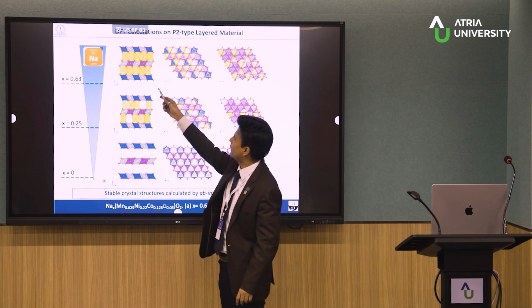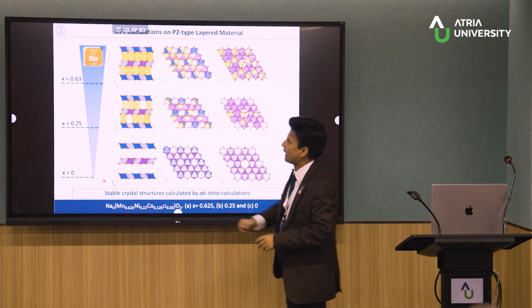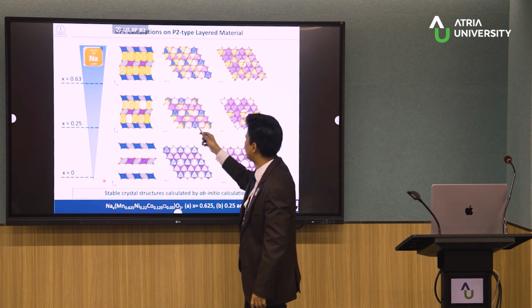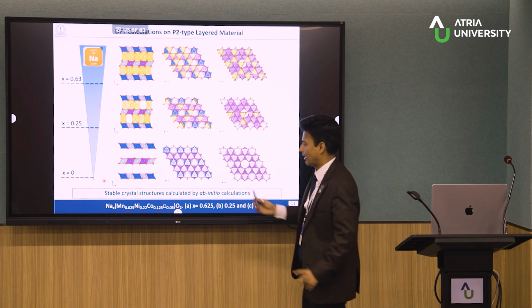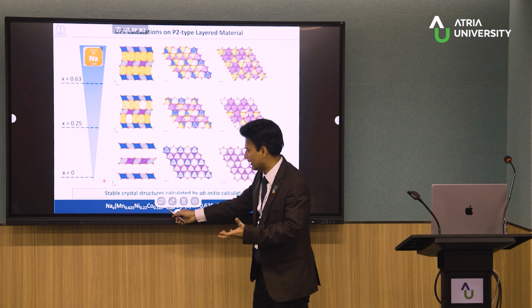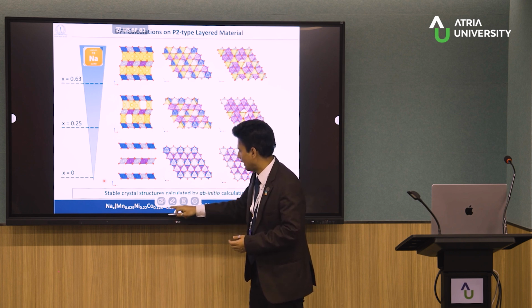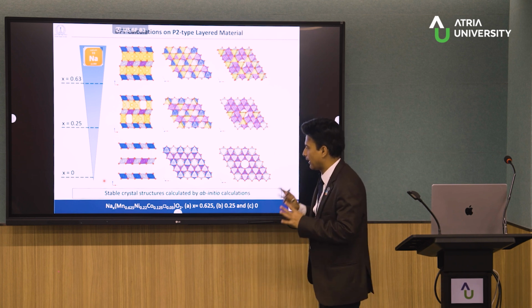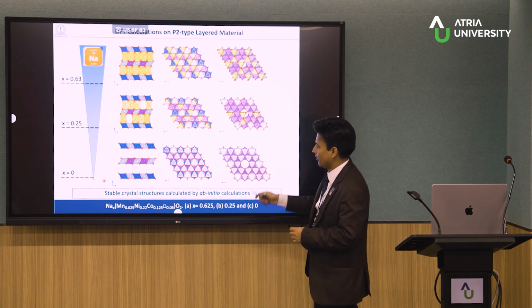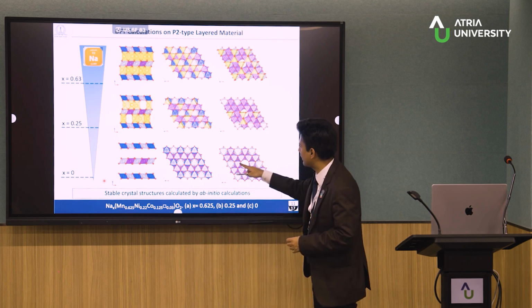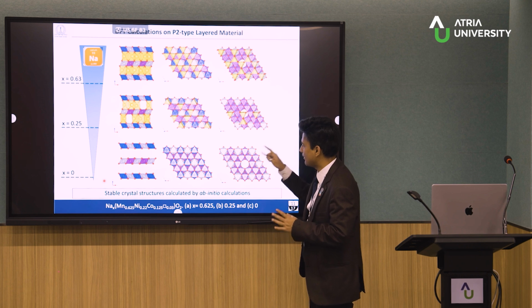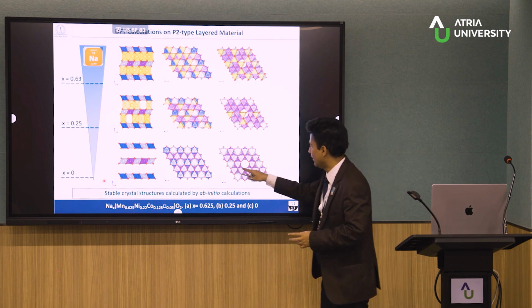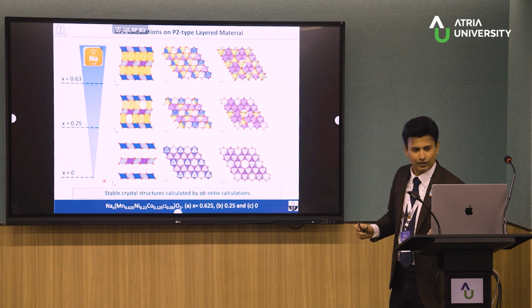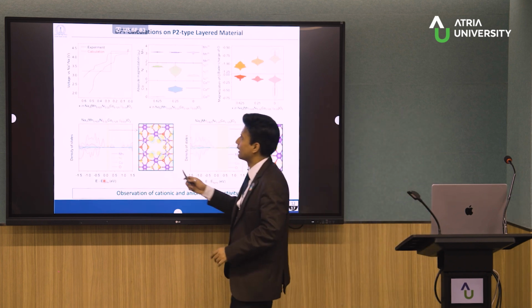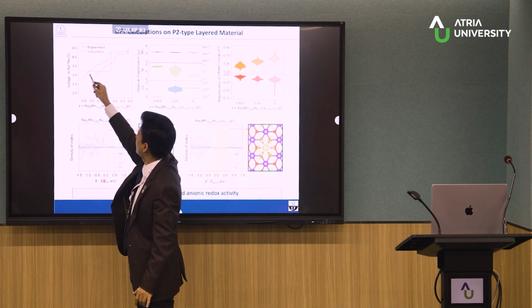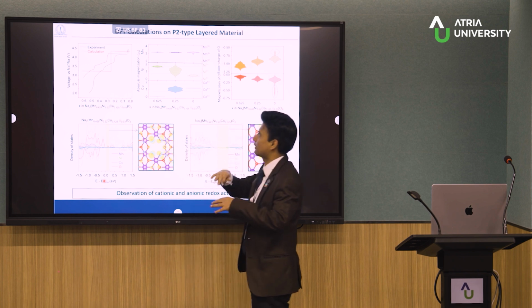So these are basically the initial structure at different perspectives, you can see, and upon desodiation, different degree of desodiation, they stabilize different structure, and they find that pretty much they are getting this kind of final composition, and sometimes some vacancies are there also in the transition metal site. Occasionally there is some vacancy. When there is a vacancy, the local electron structure can change. So these are different structures, and by DFT calculation, they can predict the voltage profile. They also get the cationic as well as the anionic redox, which is matching well with the experimental data.